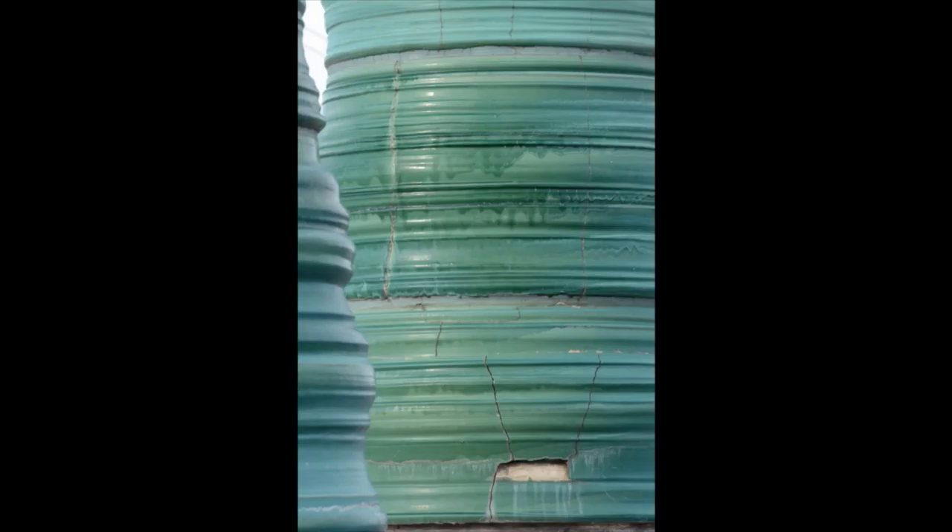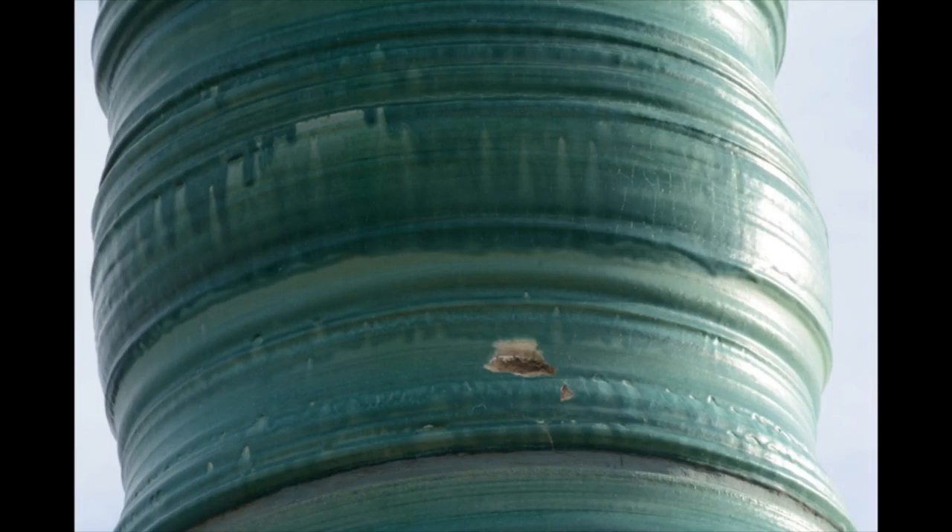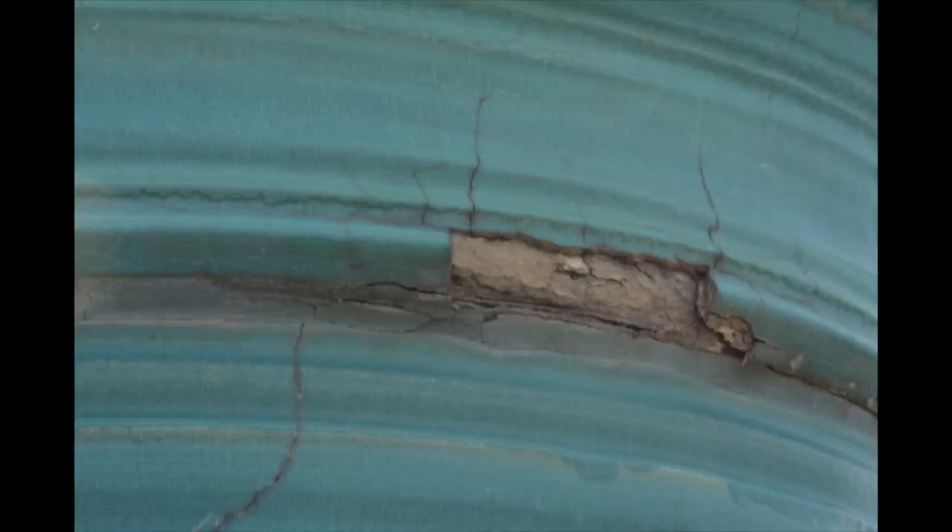Here's another view of the same flaw — this one is like 20 feet up. I think this flaw may be a rock or maybe somebody with a small gun; I'm not sure. The man-made — the interaction with man — ends up being an important aspect to outdoor work also, the way that people interact with these things, and sometimes that doesn't go as planned. The third problem with this piece is freeze-thaw. This is clearly freeze-thaw failure. This is the only place where it's actually taken the glazed surface off and is eating back in, but it's happening now, so there's going to be more.